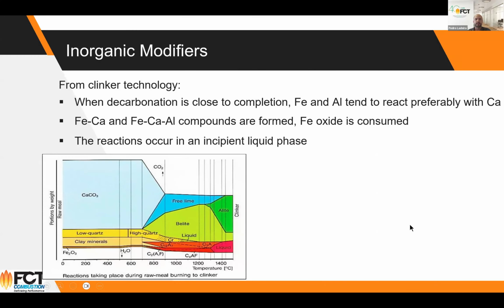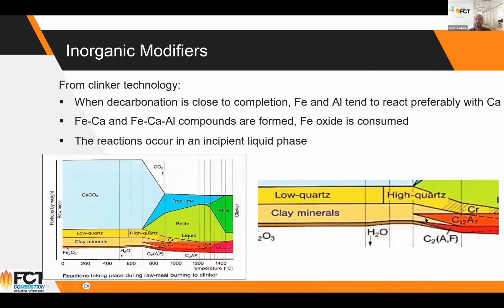So what's the rationale behind this? Let's go back into the clinker technology. When we start to heat up the feed material, we are losing CO2, while the clay phases are pretty much intact, till it gets to a point where it starts to be converted into something else. So the clay forms start to form aluminum ferrites along with calcium. These new forms being formed out of clay are the ones we are studying now. What we see is that iron, and also aluminum, tend to react preferably with calcium. So there's something about using calcium to kidnap iron. So iron, calcium, aluminum compounds are formed, and the iron oxide is consumed.